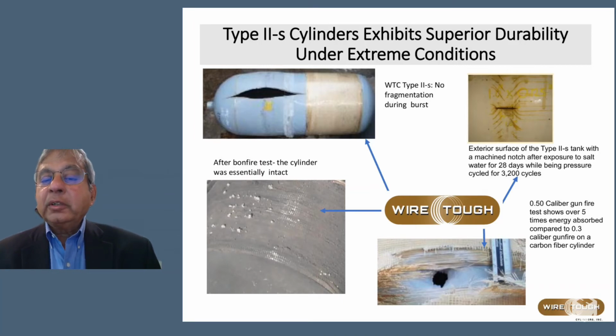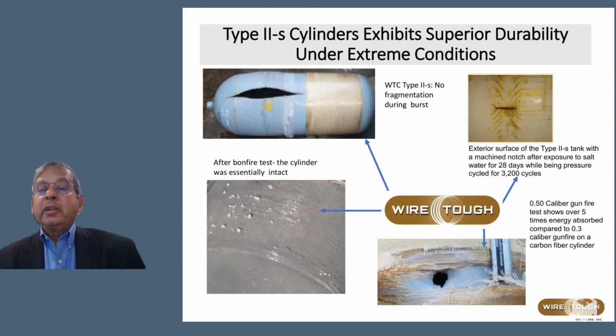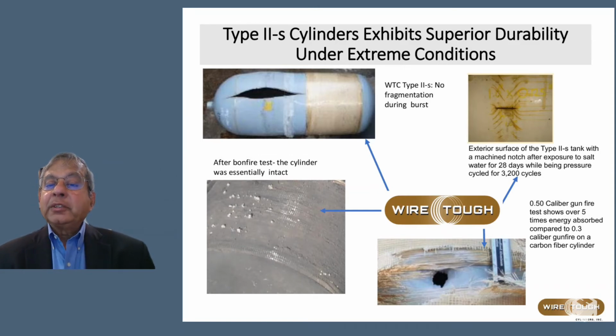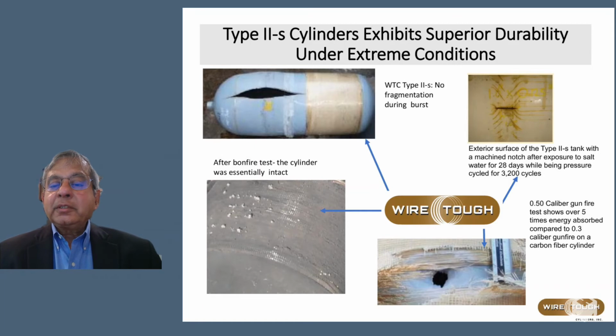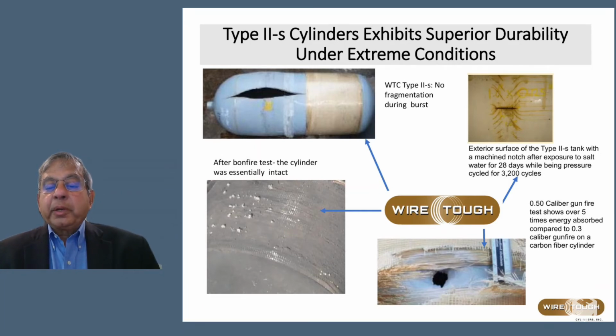Then if you look at the bottom right corner, you have the vessel after it has been shot by .5 caliber gunfire, which has over 5 times the energy absorbed compared to .3 caliber gunfire on a carbon fiber cylinder. So if you were to compare a comparable carbon fiber cylinder, .3 caliber gunfire will cause as much damage as a .5 caliber gunfire would to a steel pressure vessel. Then in the upper right-hand corner, you have the exterior surface of a Type 2S tank with a machine notch after it had been exposed to salt water for 28 days while being pressure cycled for 3,200 cycles. And you can see that there is very little damage propagation. So the upshot of all this is that we do produce a very durable pressure vessel.